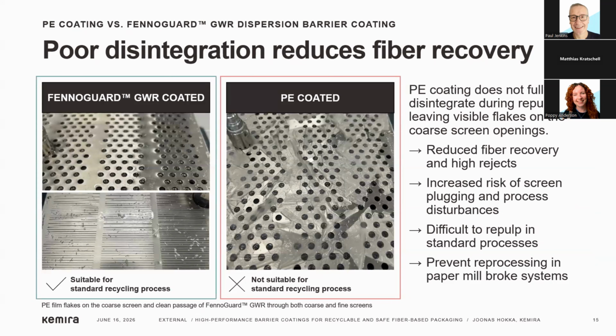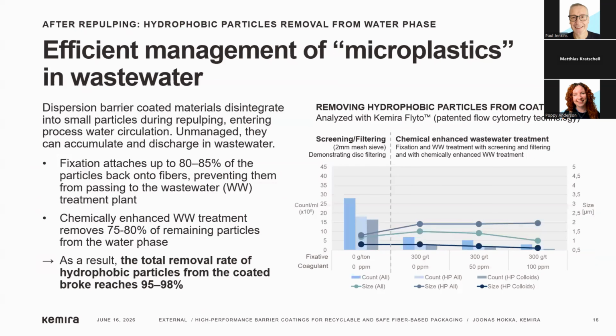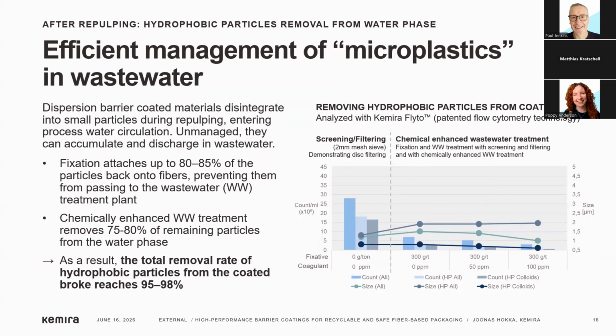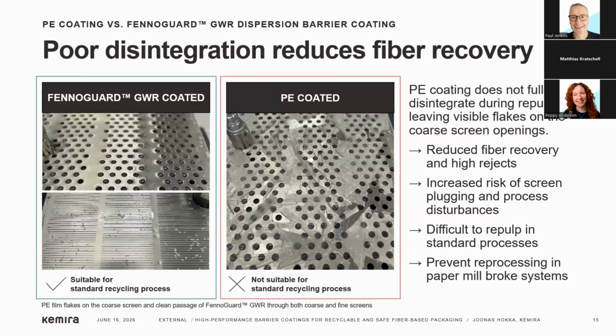So here, this slide explains where the difference exists, actually. So in the repulping process, PE coatings remain as intact plastic films. These pieces of films do not disintegrate, trap fibers, and accumulate as coarse rejects on screens. This leads to fiber losses, screen plugging, and process instability.